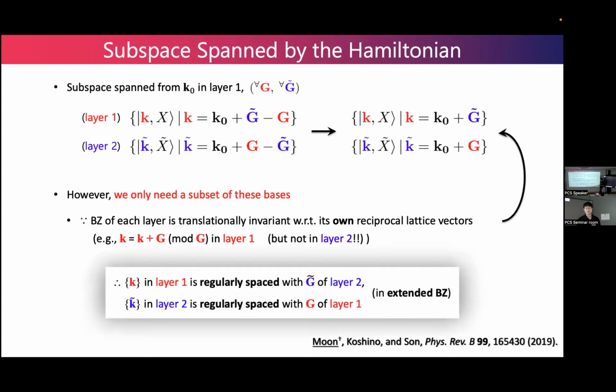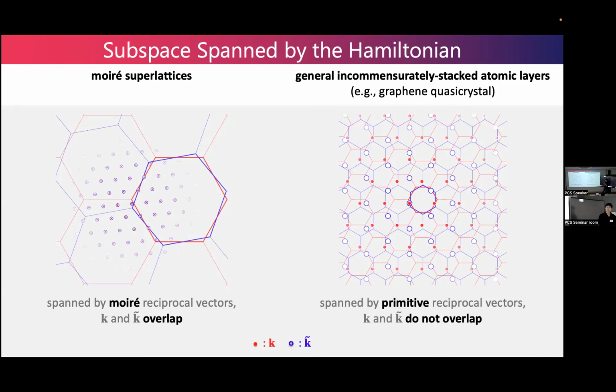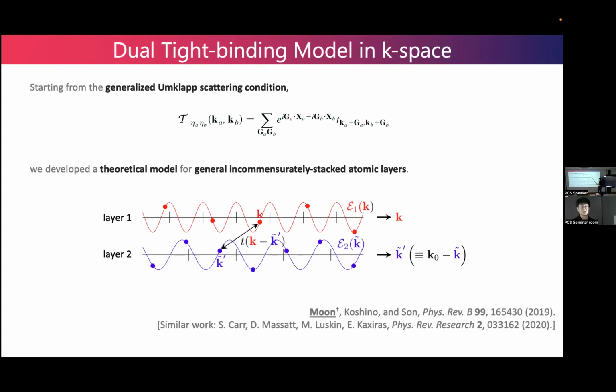And K in layer 1 is expanded by the G vectors of the reciprocal lattice of layer 2, and K in layer 2 is expanded by the vectors of layer 1. So unlike the periodic choice of subspace in the periodic system, we choose the subspace in the primitive lattice vectors, and the K and K tilde do not overlap. By doing this, we can develop the theoretical model for general configurations, and it makes a tight-binding-like form in the momentum space.